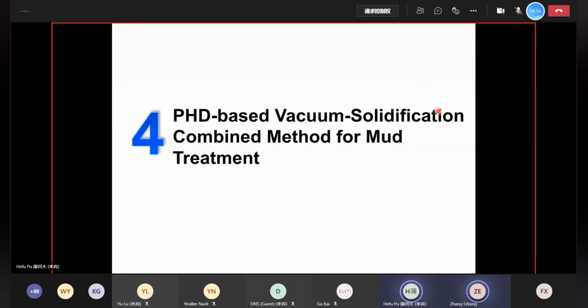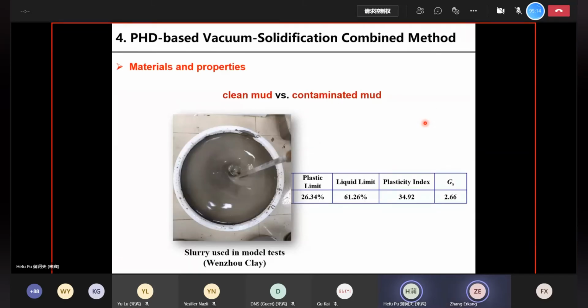So in section 4, I will present some PHD-based vacuum and solidification combined method for mud treatment. In this case, on top of the vacuum preloading, we add in a solidifier to further increase the strength. This is the mud slurry that we use. In this section, we test both clean mud and also contaminated mud. For the clean mud, we primarily look at the dewatering efficiency and the mechanical behavior, such as the shear strength. For the contaminated mud, on top of that, we also look at the stabilization effect of the heavy metals.